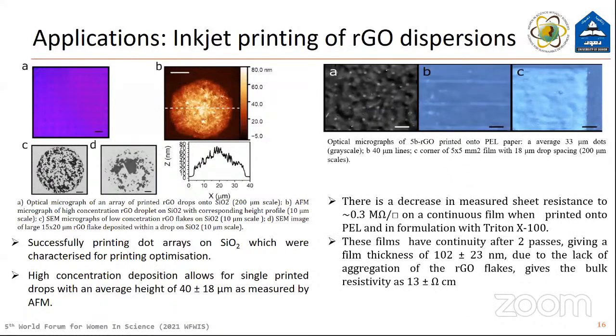We also tested this on PEL paper just to see if it's printable or not. And luckily it was printable. There is a decrease in measured sheet resistance to 0.3 megaohm per square on a continuous film when printed onto PEL in formulation with Triton X. These films have continuity after 2 passes, given a film thickness of 102 plus or minus 23 nanometers, and due to the lack of aggregation of the RGO flakes, this gives the bulk resistivity as 13 plus or minus ohm centimeter.